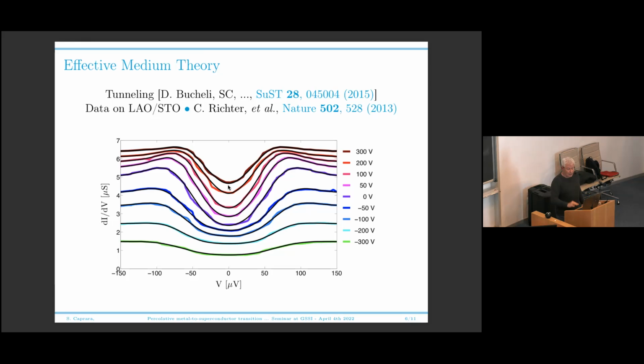There is a very large value at zero bias. Usually in a superconductor, the zero bias value goes to zero or very close to zero. Here, you have a very large value of the zero bias tunneling conductance. And in our opinion, this is nothing but the result that even in the superconducting phase, you have a sizable fraction of your system that is still metallic. Even when superconductivity percolates, you have a fraction of your system that for some reasons stayed metallic down to T equals zero. And this is a good explanation for the zero bias conductance in the system.